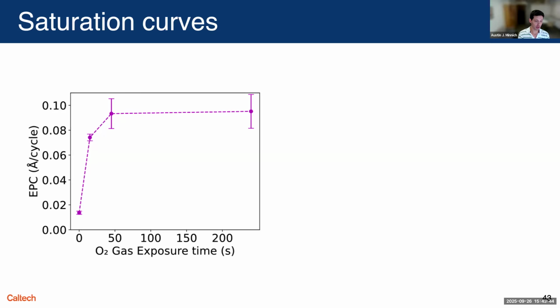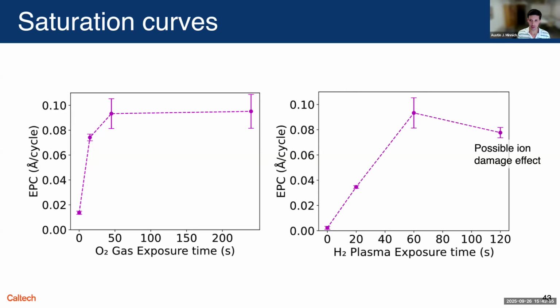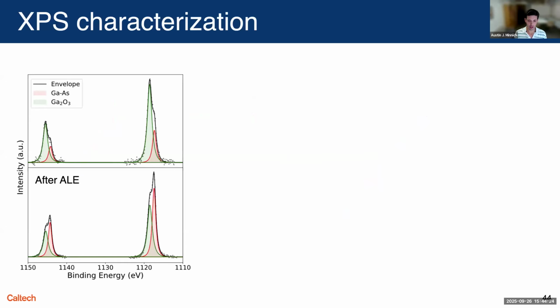So here I'm plotting the etch per cycle on Y versus the oxygen gas exposure time. And you can see after a certain amount of time, there's no additional etching. And roughly for the hydrogen exposure time, you see basically the same thing within the uncertainty. There's a point at the right which is unexpectedly lower, but we attribute this to probably the ion damage due to the longer exposure time. But basically within the uncertainty, we do see the same thing for the hydrogen. So this basically says that this is indeed atomic layer etching.